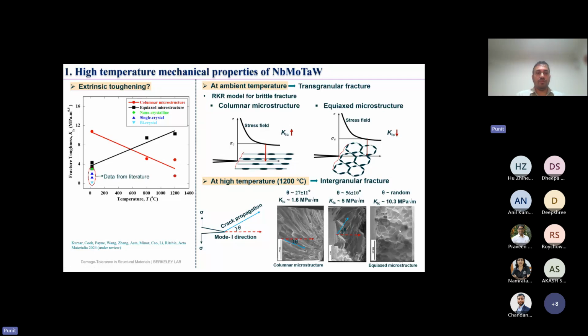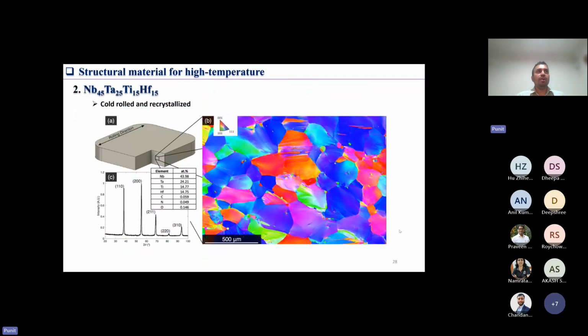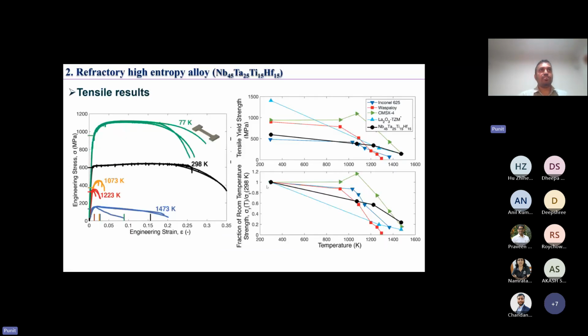Although we have a very poor fracture resistance, we are still able to recover some fracture resistance through extensive toughening of this material. So coming to the second alloy, which is niobium, tantalum, titanium, hafnium. This material was ductile, as I talked about initially, and it was so ductile that we were actually able to cold roll blocks of this material, and we were able to recrystallize the grains through heat treatment at about 1100 degrees C. So we went ahead and did some tensile tests on this material.